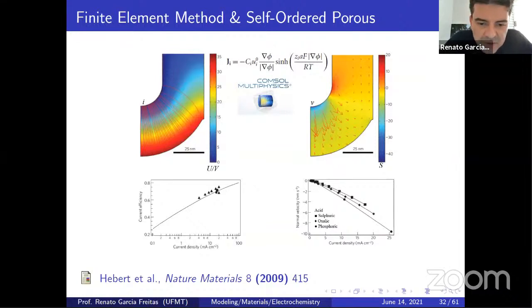And Professor Hebert published in 2009, using the finite element method, using COMSOL, they solved this differential equation where the flux of current is minus concentration times mobility, the gradient of flux, a hyperbolic function of this part, and they observed the flat parts of the current as observed here, and here the stress and the diffusion, the normal velocity of diffusion of these pulses. I cannot read this part because it doesn't allow me, but it was aluminum oxide. But it's an oxide, and the phenomenon of nanopores or nanotube anodization is quite similar.